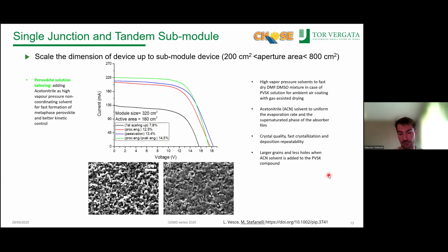So the phase in which the perovskite starts to seed and start the crystallization. The addition of ACN is due to a couple of reasons. The first one is that we want an evaporation rate that is uniform on the whole area. And the second thing is that we want milder conditions for the quenching of our film, especially for the air blade, because in this case, the size of the module was really close to the limit of our machine. So we need to put lower pressure in our air knife just to not have strange effects on the film,